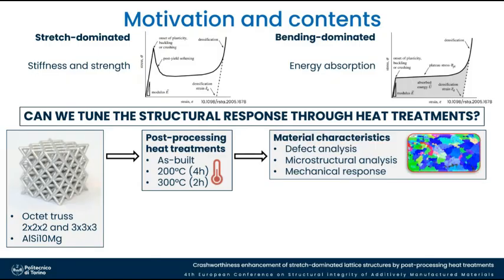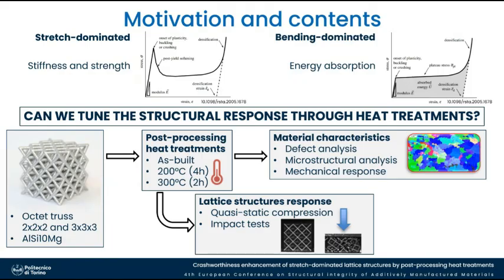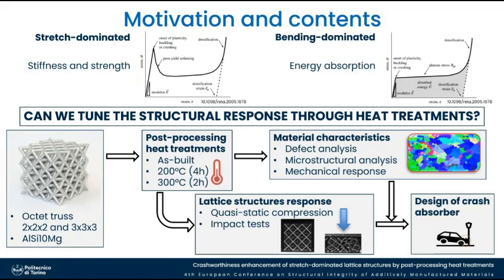We characterized the material in terms of defect population, grain size, and the mechanical response in terms of tensile test, basically. And then we tested the lattice structure under compression, performing quasi-static compression and impact tests. And from that, we identified the most suitable heat treatment for our, let's say, energy absorption application. And then through that, we also designed a crash absorber for an automotive application.